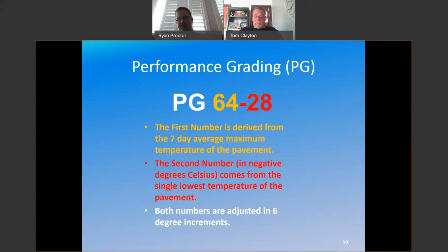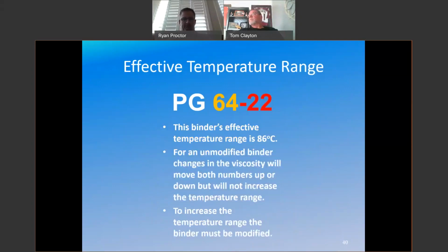And then both of these numbers are adjusted in 6-degree increments. So I'll give you an example. I don't have it in here. If you looked at your weather temperature, you looked at traffic, you might find out you needed a 61 minus 24. Well, people don't supply 61 minus 24s. If we did that, we would have to have significantly more tankage at these terminals, at the hot mix plant and at the asphalt terminal. You round up and you end up with a 64 minus 28.